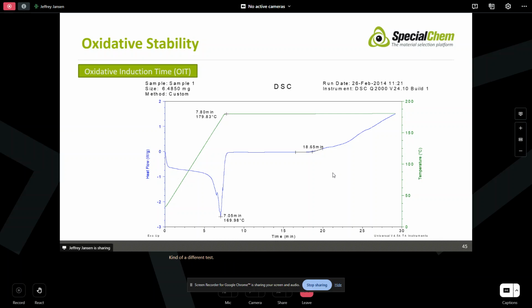Now a different test from all the rest, one that uses a different type of experiment, is oxidative induction time, or OIT. Basically, we heat the sample up, and here I've got temperature thrown in. We're going to look at time on the x-axis, but I've also got temperature so we can see what happens. We're heating the sample up in a nitrogen atmosphere, and then we hold it isothermal, and then we turn on oxygen or air, but very commonly oxygen. And then we measure the time from this point to that point.